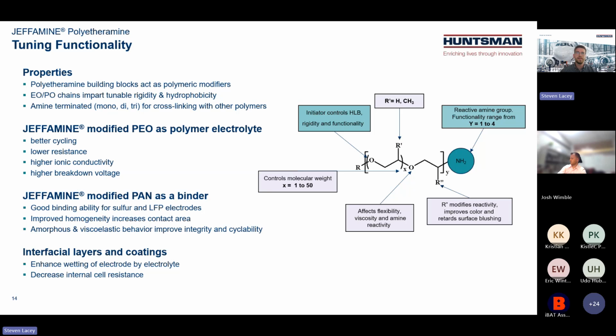So with these polyetheramine building blocks, you can modify them heavily. So the tunability here is very wide. You can change the EO-PO chains and also the ratio between them to enable different hydrophilicity or hydrophobicity and different rigidity. Also, EO, so ethylene oxide, provides the ionic conductivity that you would need, for instance, in the battery electrolyte, while PO actually decreases the crystallinity. So in this case, you could have a more flexible material that can possibly cover more contact area.